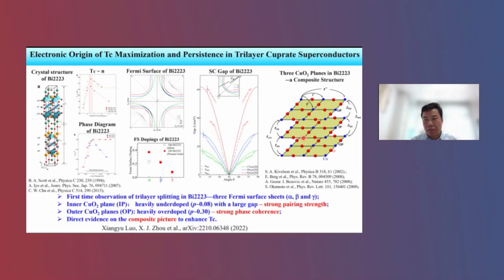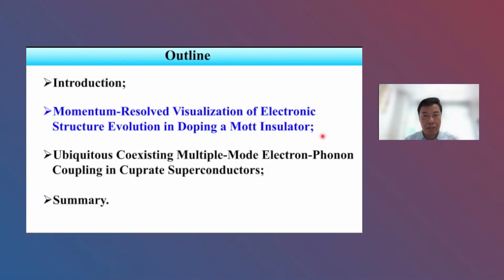But actually, it can act as a strong phase coherence source. So this composite picture means you have the strong pairing strength layer and also the strong phase coherence layers combined together. You can really reach high Tc. So I think this work really provides strong evidence that the composite picture is right, and it is also a good way to enhance Tc.